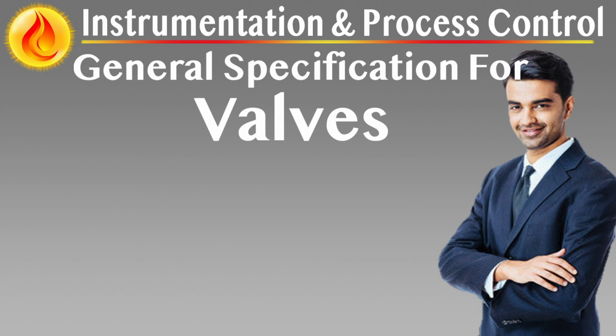Valves exposed to sour or wet hydrogen sulfide service must comply with NACE MR0175, ISO 15156 requirements. All pressure-retaining parts must demonstrate hydrogen-induced cracking resistance. Austenitic and duplex stainless steels must be supplied in solution annealed and quenched condition. For CRA weld overlays and cladding, execution shall be as per industry practices and must pass appropriate quality control checks such as dye penetrant testing and hardness verification.